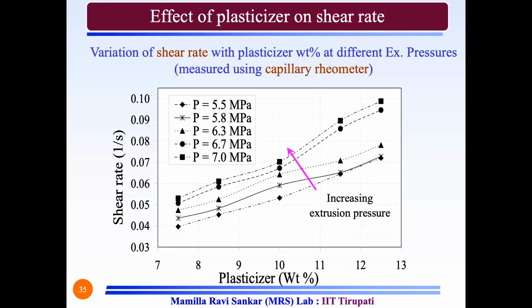So now we have measured with respect to various plasticizers. Normally, plasticizers are low molecular weight materials. You don't bother about all these things. But by using the equations we have seen in the capillary rheometer, we can measure the shear rates. From this experiment, the most important thing is measuring the shear rate, and you have to observe what range of shear rates your particular experiment is working in. Okay, you may be measuring the shear rates in one range and doing your further experiments in another range. That should not happen.